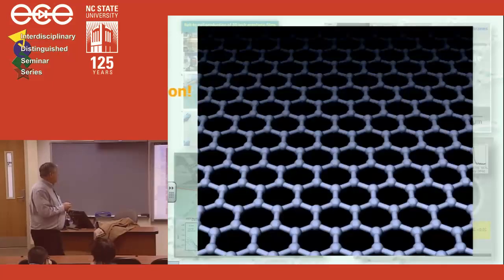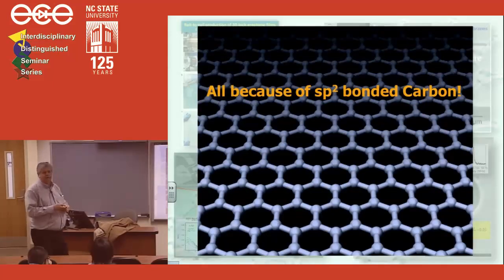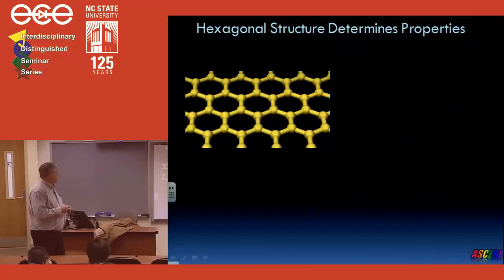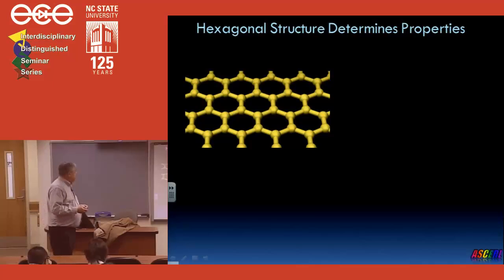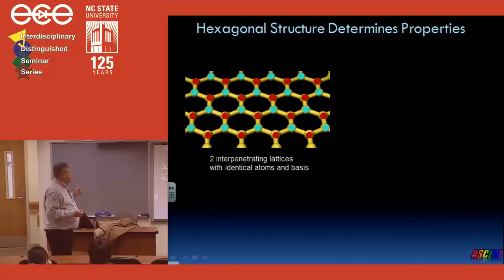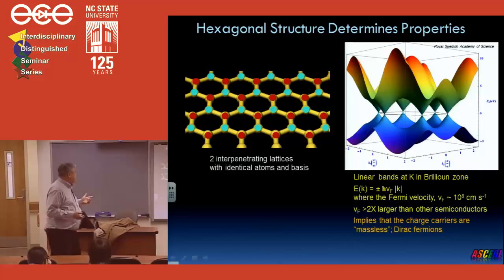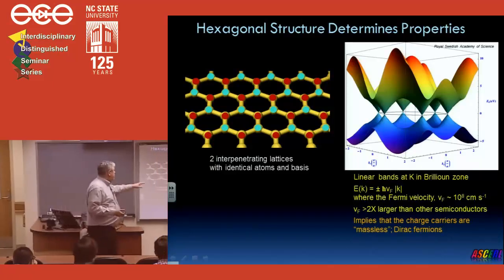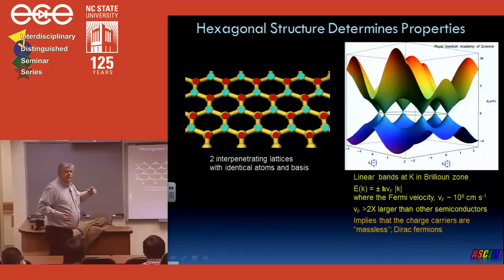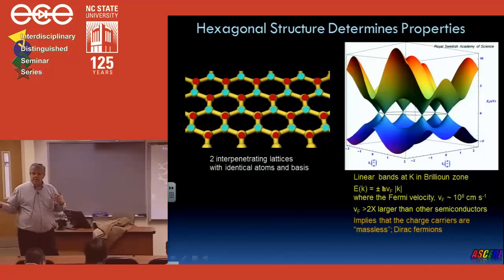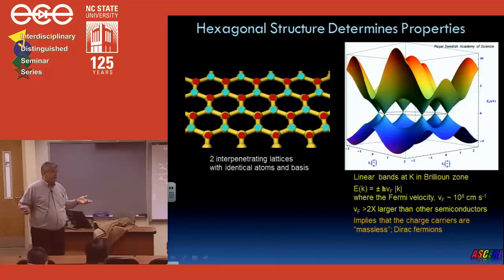So all of this is because of sp2 bonded carbon. And a brief primer on what sp2 bonding gives us. The hexagonal structure consists of 2 interpenetrating lattices, so it's a 2-atom basis. And when you calculate the band structure, which was done in the 40s, you get linear bands in the vicinity of the K point in the Brillouin zone. And a linear band structure means that the effective mass of the carriers is 0.